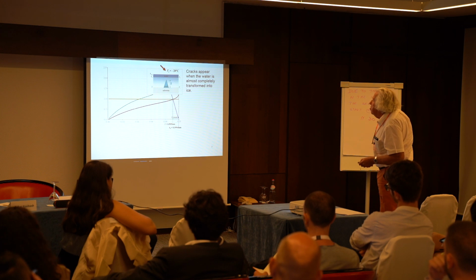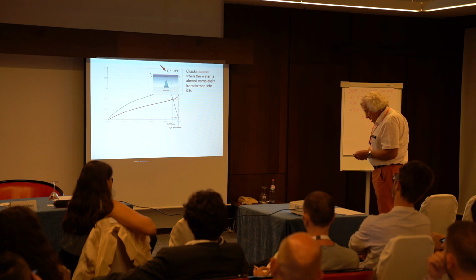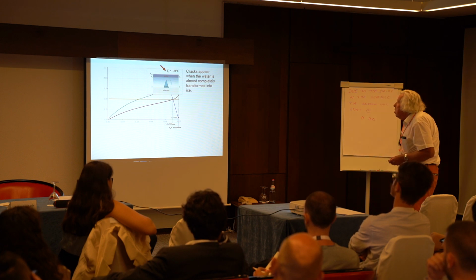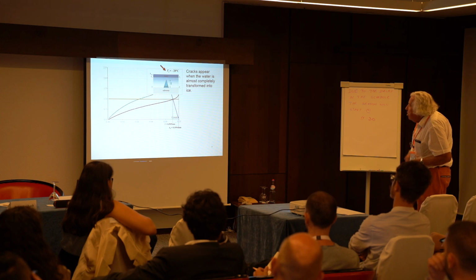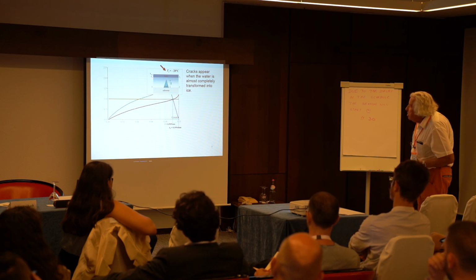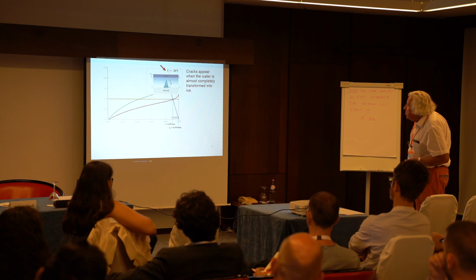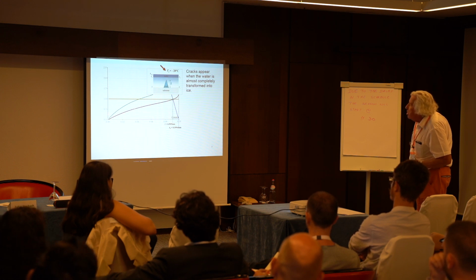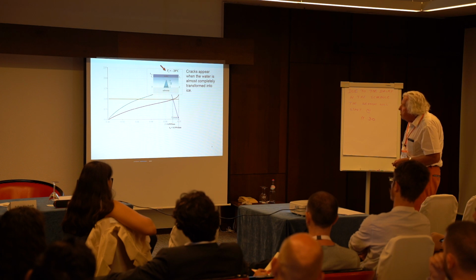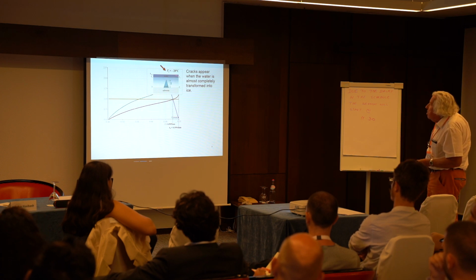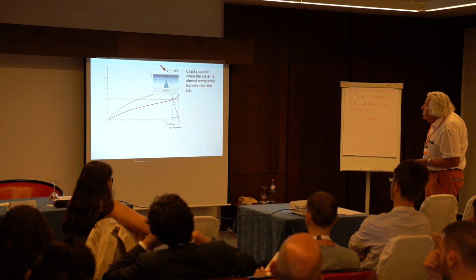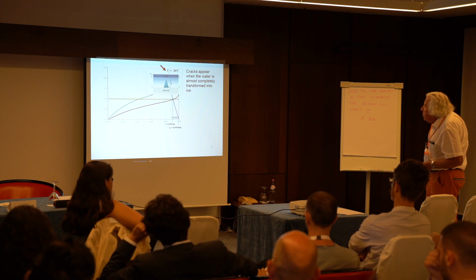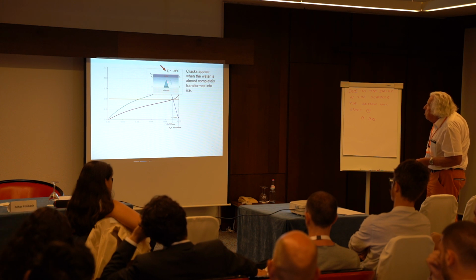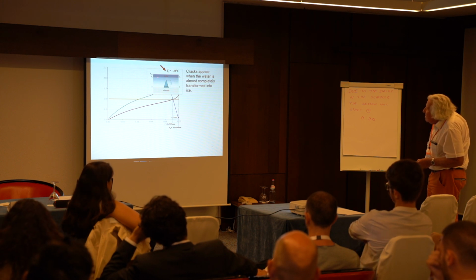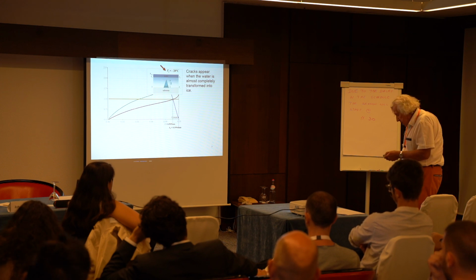Okay, so we have the parameters. We can try to use the coupled criterion. This is obtained for a temperature of minus 20 degrees Celsius. Okay, fortunately the figure is here. The blue line is the stress condition. This one is the energy condition, G incremental, and this is G. But indeed, we ignore G. So you see that for minus 20 degrees Celsius, we have an initiation at this length, more or less when the water has turned into ice more or less completely.